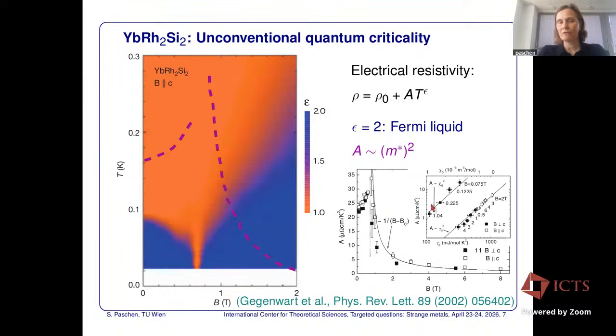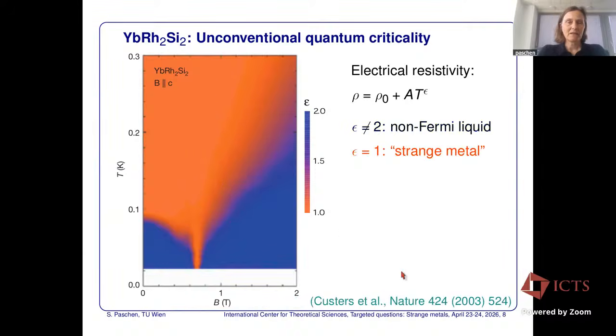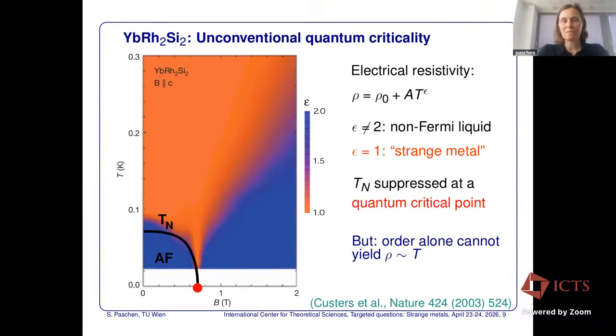That's not only true for the A coefficient, but in heavy fermions, we very frequently have this similarity, the Kadowaki-Woods and Sommerfeld-Wilson scalings. That means the specific heat and the Pauli susceptibility follow precisely what the A coefficient of the resistivity is doing, and that's shown in this inset here. Then if we are looking at the orange, that is where the resistivity is strictly linear in temperature, and that's our strange metal. So what else is there in the phase diagram? Indeed, there is a Néel transition. Yet we argue that this is not what drives the strange metallicity.